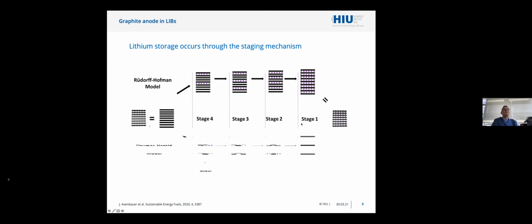happens. So when we have a small amount of lithium, we have a rather high voltage versus the lithium plating potential, and then we hit a second region where we have stage 3, and then the following region, stage 2, and then at the very end we have stage 1, where all layers are full with lithium. And we can very well observe these plateaus, especially if we use low or moderate current rates.